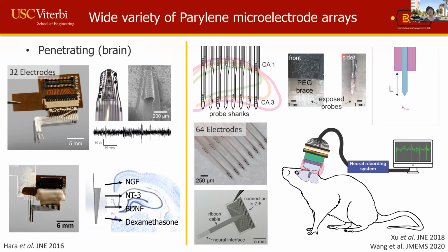So this device is intended to interface with the hippocampus and different regions of the hippocampus that are involved in memory formation. And so you can kind of see that these pastel overlays are taken from a rat brain atlas. And these electrodes are actually placed specifically to match the anatomy that we pull from the atlas. And so we call these conformal electrode arrays. Here we have 8 tines, each with 8 electrodes for a total of 64 on this device. And I'm showing you the tip as well as the back end where we actually connect to